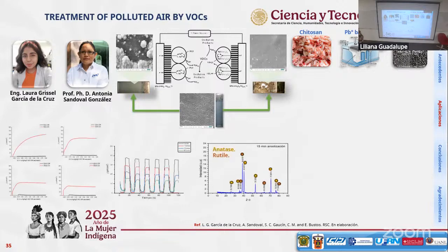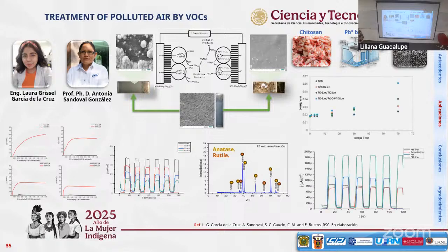In the laboratory, we are now characterizing these modified surfaces, and we verified that it's important to have the anatase and rutile phases in the titanium dioxide nanotubes. It is good to have them and promote photoelectrocatalysis. That's why we developed this, because we want to integrate the ultraviolet lamp directly inside the electrochemical reactor. With these modifications we promote a good current density, which promotes the destruction and removal of volatile organic compounds, with good stability over time.